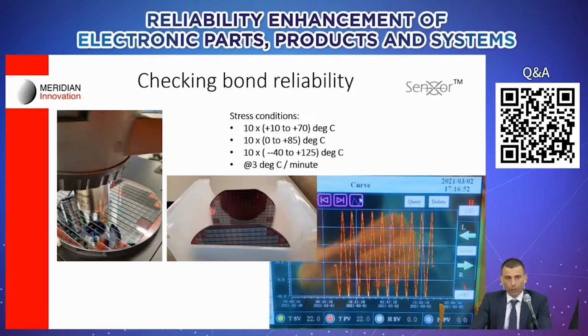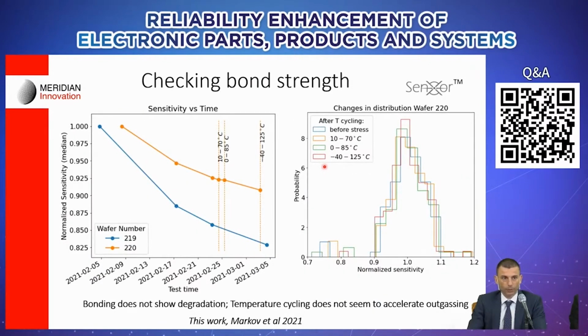are put in a chamber. We would typically have a control wafer that sits outside, doesn't undergo temperature stress or cycling, and other wafers of similar wafer maps and similar sensitivities and process for producing that undergo temperature cycling. In this case, it's different temperature extremes, but 10 cycles at the same temperature ramp, around 3 degrees per minute, which is the range that we can afford with our equipment.